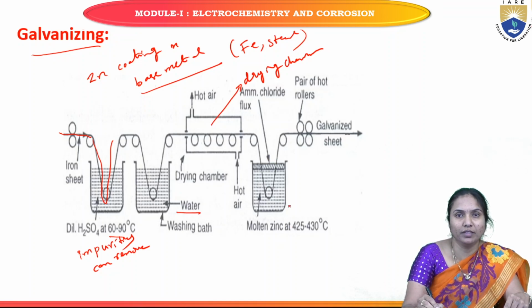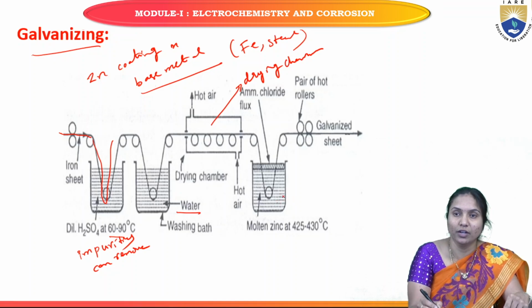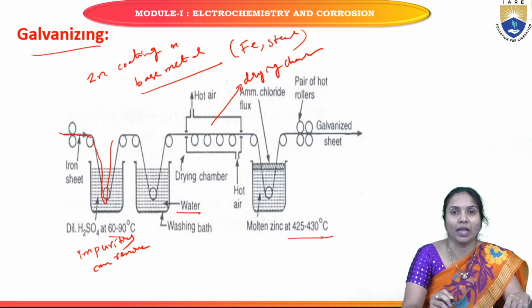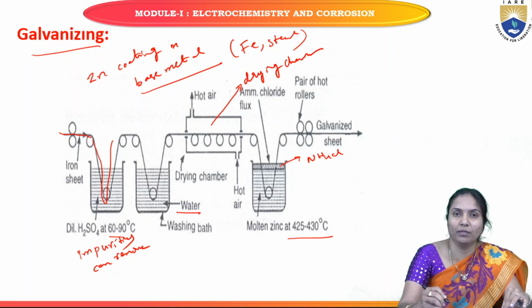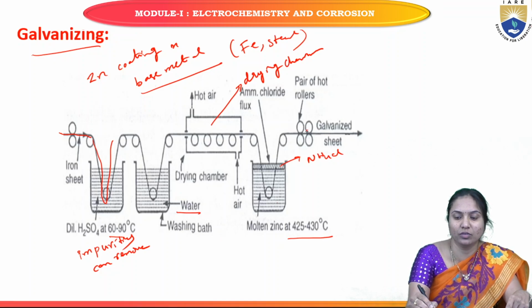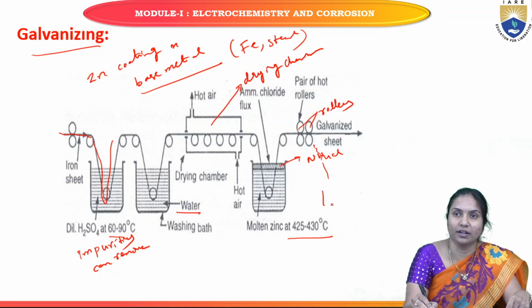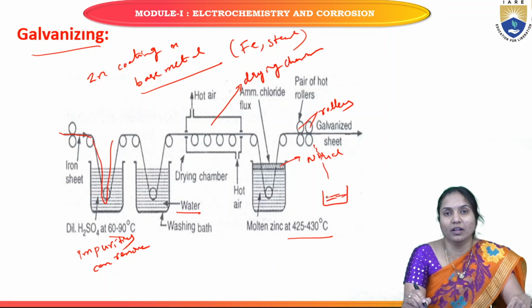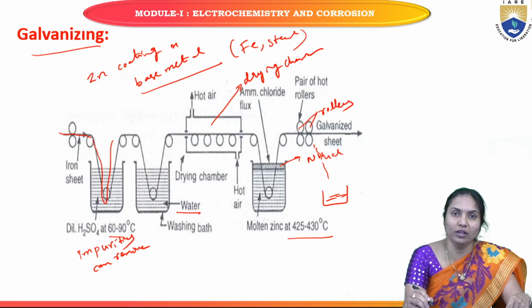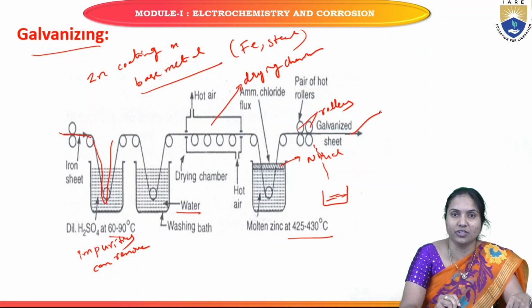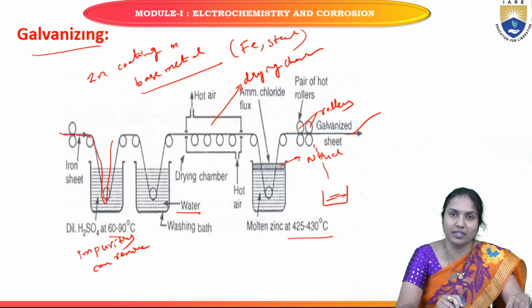Next, the iron article is dipped in the molten zinc bath, maintaining a temperature of 425 to 430 degrees centigrade, and this molten zinc bath is covered with ammonium chloride flux. After some time a uniform layer is formed on the base metal surface. Next, excess zinc is removed when we pass it through the pair of rollers. Finally we go to the drying chamber and slowly cool. After that we finally get galvanized iron sheet. This process is called galvanizing.